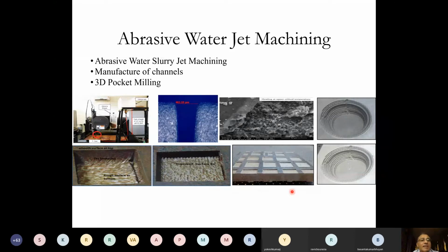The objective of this entire exercise was to make micro channels, because without slurry, if you use just abrasive water jet, the kerf angle is very large. It becomes very tapered. So you can see this image. This is relatively very controlled. This is the vertical image. This is the depth of the channel being created, and this is the width of the channel.